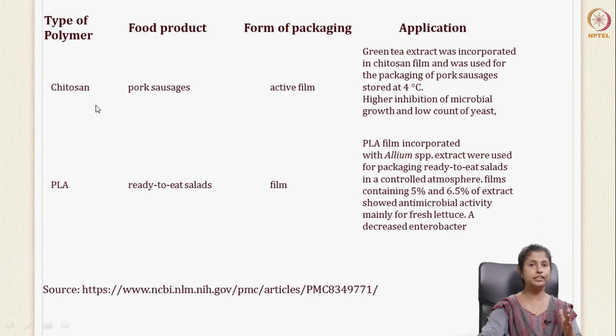Further, they again used chitosan in pork sausages as an active film. Green tea extract was incorporated in the chitosan film. So in the edible film itself, you could incorporate whatever component you want. In this case, they incorporated green tea extract, and this was used to package pork sausages stored at 4 degrees centigrade. They saw high inhibition of microbial growth and a low count of yeast.